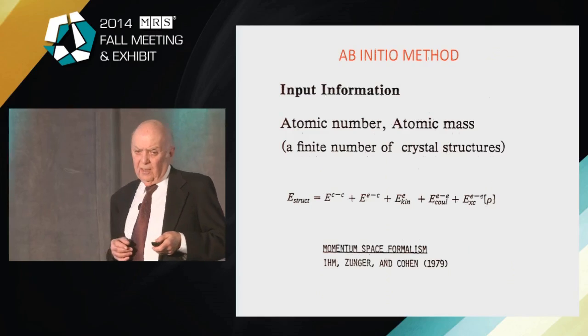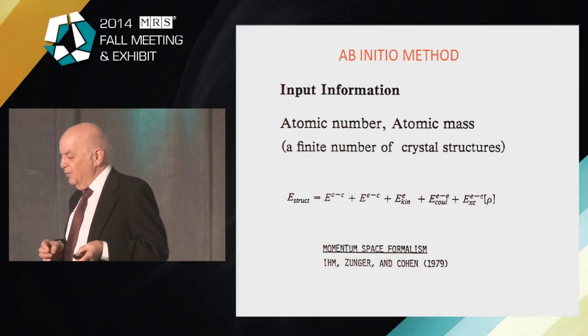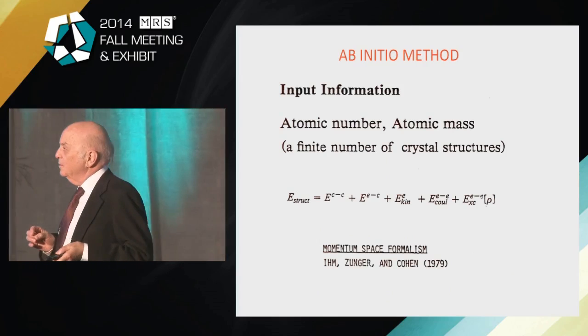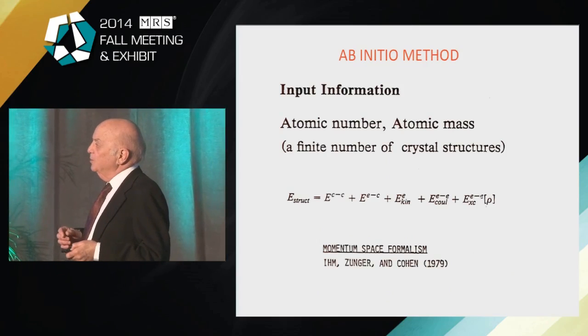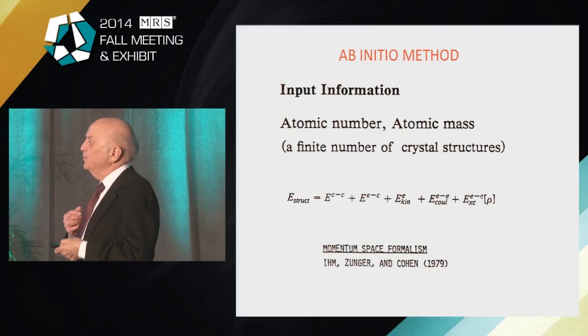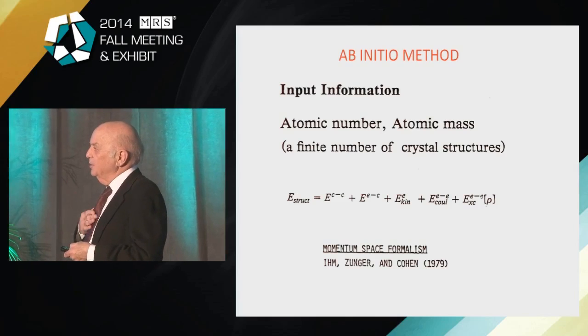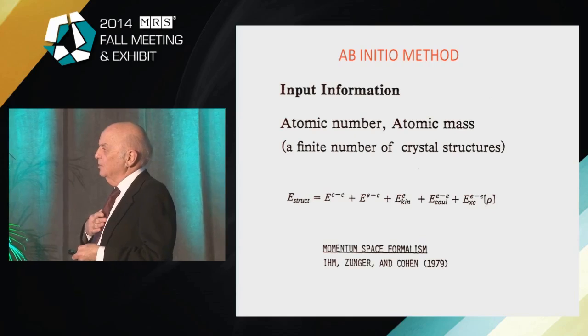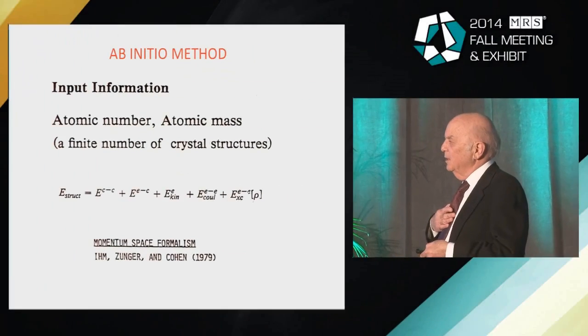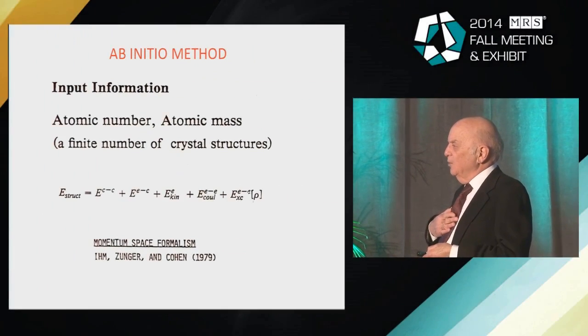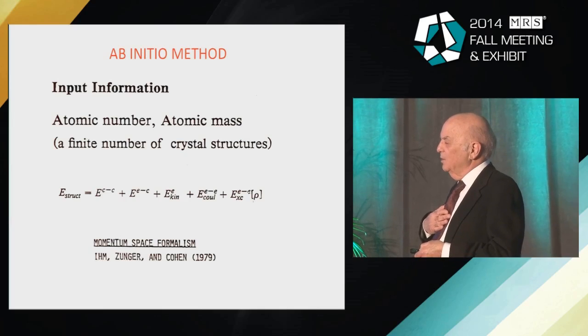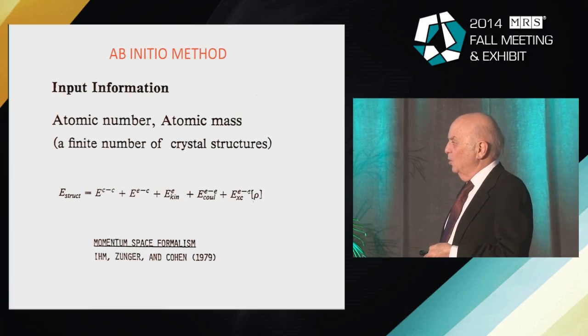But a true ab initio calculation has to start with just input about the atoms. So for the ab initio approach, all you want to use is the atomic number to generate that potential, the atomic mass if you're looking at vibrations, and you test different crystal structures. And you can calculate, when you put all the atoms in their proper place, the total energy of a system. So you have the cores interacting with each other, that energy, the cores interacting with the electrons, the kinetic energy of the electrons, the Coulomb interaction of the electrons. This is electrons.